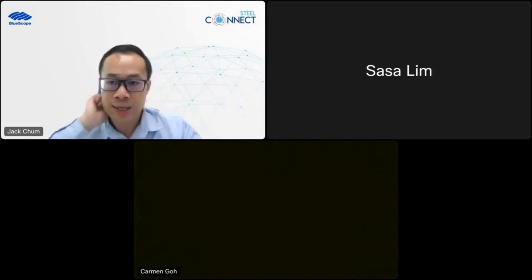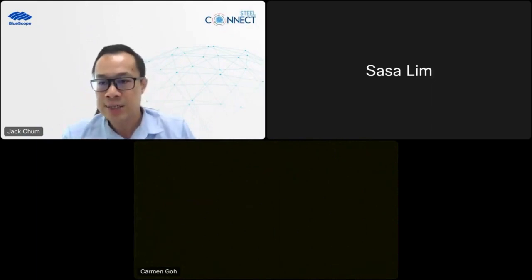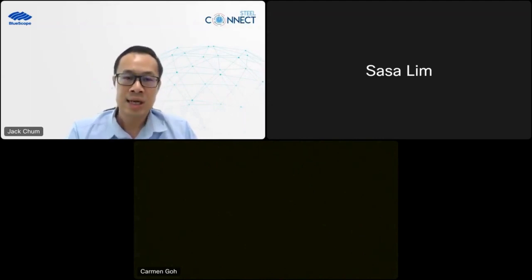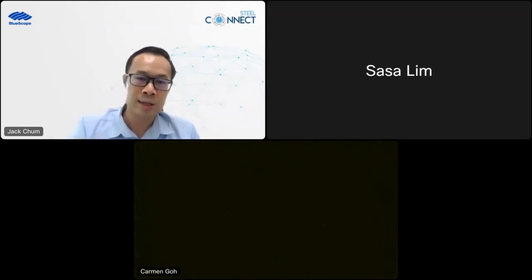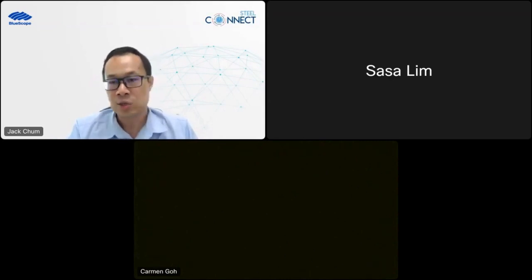Okay. To me, currently in Malaysia itself, we don't have a corrosion map. So what we can use is only based on our past experiences and data collection that we are currently having. So just now I mentioned the rule of thumb, right? The 1 kilometer rule is still applicable in Malaysia climates. Anything below 1 kilometer from a coastal area is considered as C3 or C4 category already, or even C5. C5 actually means something like 100 meters from a coastal area. It's very, very corrosive. So this is the simple guideline that I can share back to you.